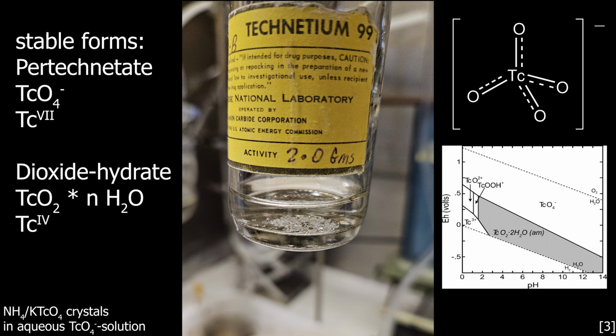In contrast to the pertechnetate, this form is poorly soluble in water and significantly less mobile. The reduced mobility can be explained by the fact that technetium 4+ interacts well with surfaces. It would be very handy if we could convert the pertechnetate into this technetium dioxide hydrate. However, that does not just simply happen.